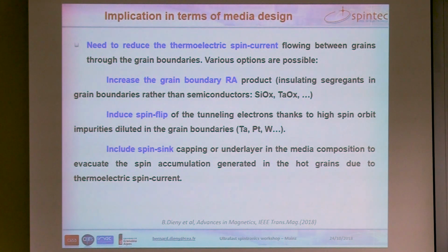Something else which can be done actually is to try to reduce the spin polarization of the electrons tunneling through the grain boundaries. So this can be done by inducing spin flip in the grain boundaries. So here we can try to incorporate in the grain boundaries heavy metal elements like tantalum, platinum, tungsten, which have high spin orbit coupling. But these elements have to segregate inside the grain boundary material to actually induce this spin flip at the grain boundary. And then something else which can be done is to include spin sink above and or below the recording layer. For instance, if we include a platinum layer, this platinum layer, which has a strong spin orbit, can actually pump out the spin accumulation which is built up in the hot grain during the cooling of the hot grain.